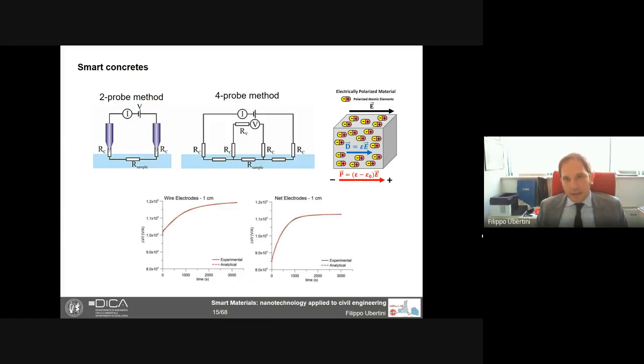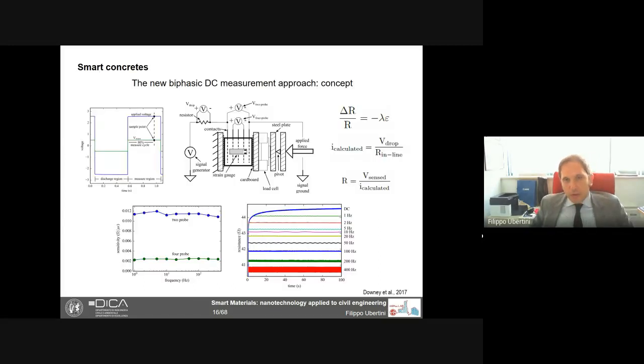Of course, the alternative is to do AC, to do alternated current, but then we cannot really go to multi-channel reading. So one main contribution we have done in the work by Downey and co-authors was proposing a biphasic direct current measurement that keeps the advantages of DC but removes the polarization issue. So we can do multi-channel reading, but we don't have any polarization issue.